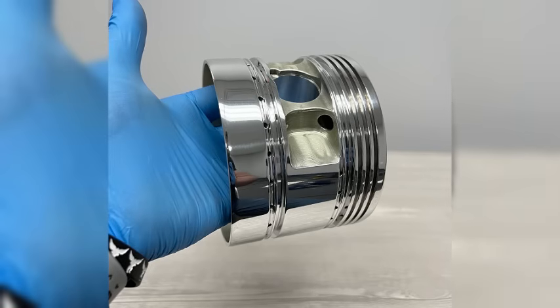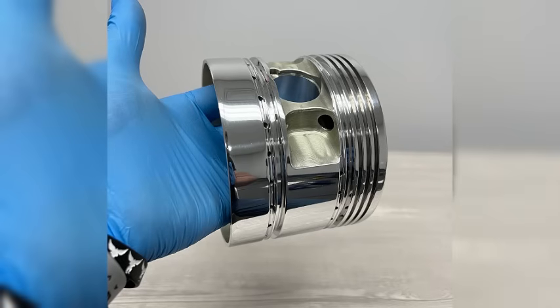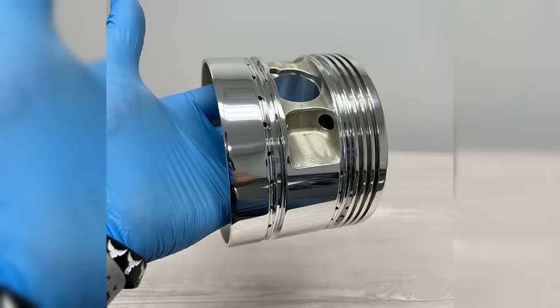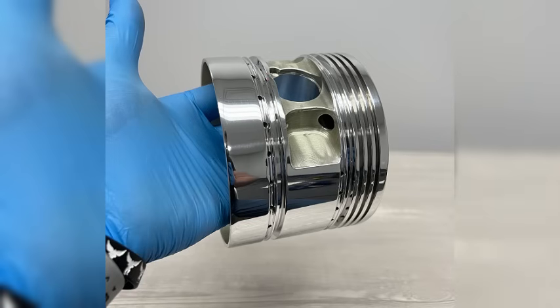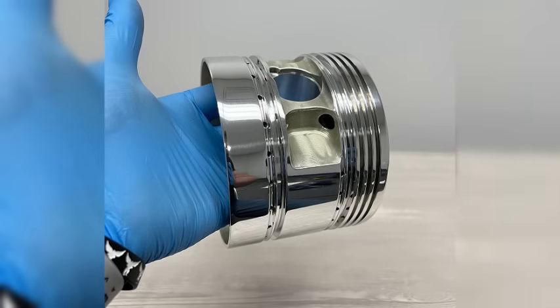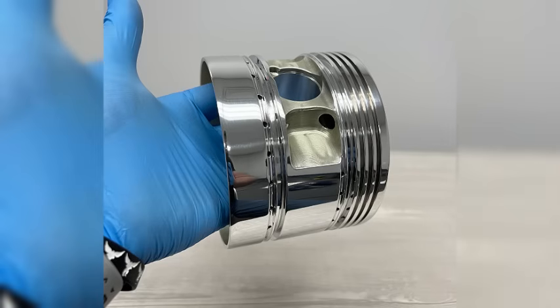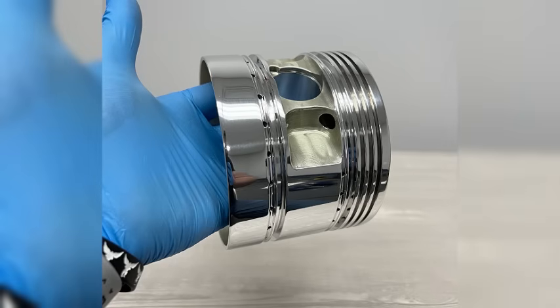When Packard received a license to build a Merlin in 1940, they initially tried to source rings from American suppliers. The results were disastrous. Rings from automotive suppliers failed within hours in Merlin test engines. The metallurgy wasn't right, the iron was too soft or too brittle, or didn't have the correct carbon structure. Heat treatment was inconsistent. Quality control was inadequate for aircraft standards. Packard tried importing rings from Rolls-Royce in England. This worked, but it was clearly unsustainable.